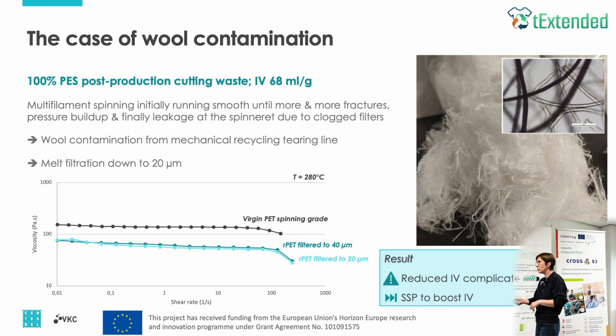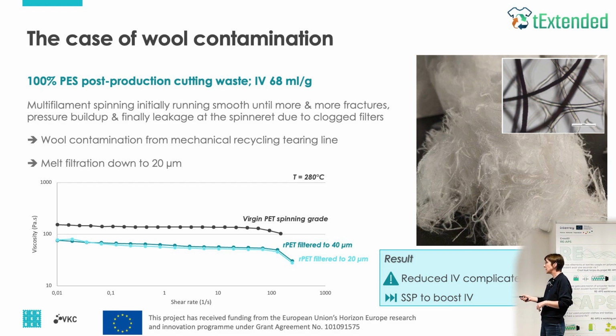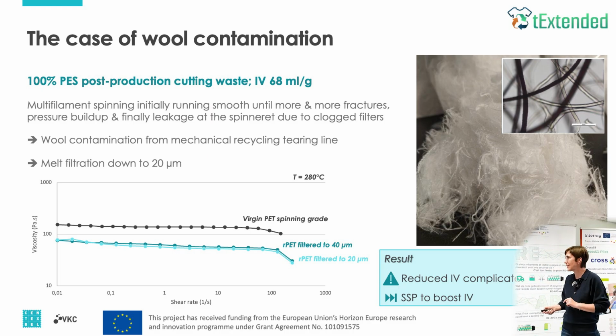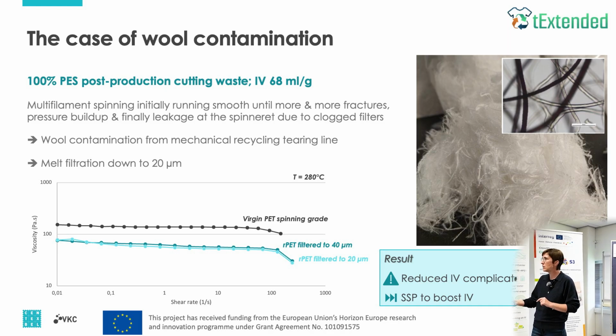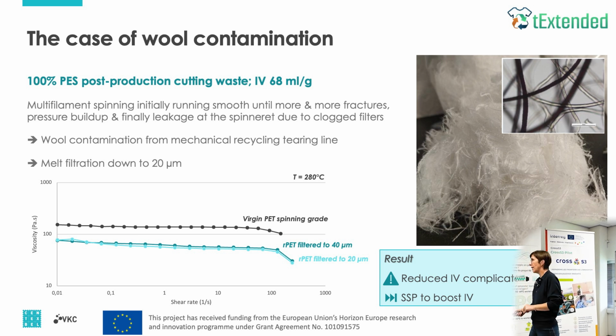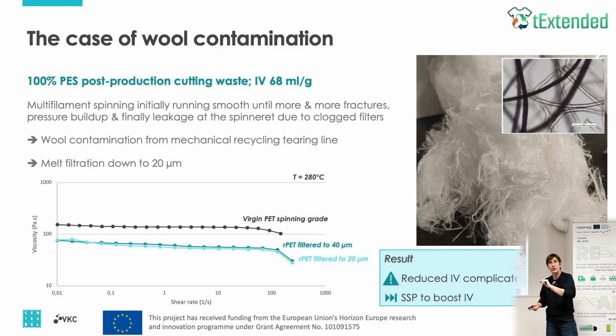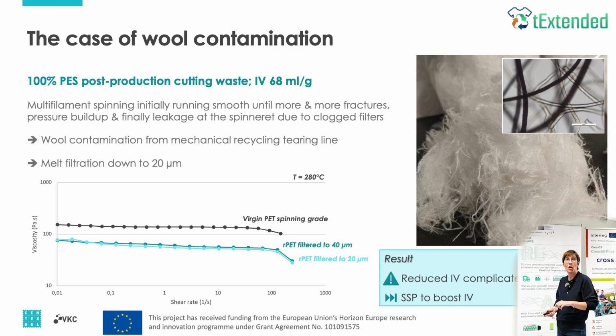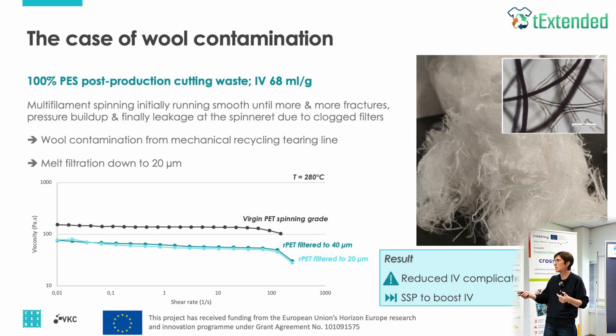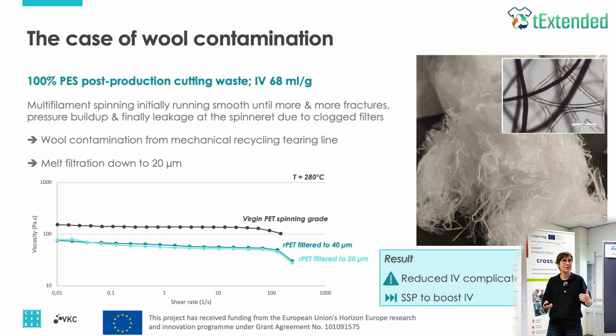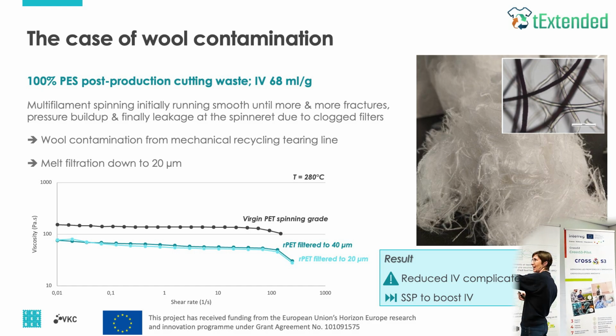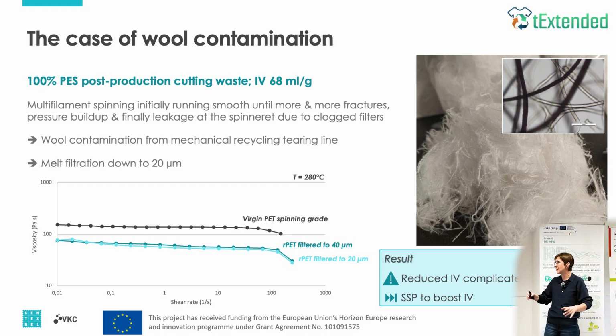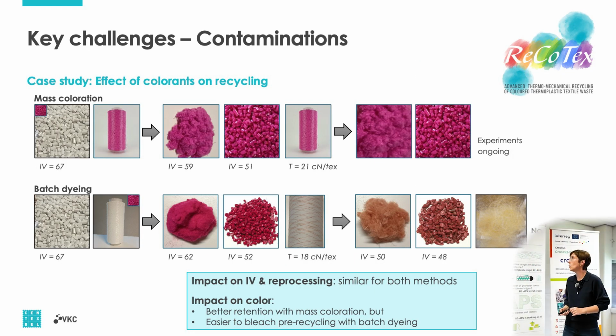Then okay, you can say we can try to filter it out, so we try to filter with a 20 micrometer and 40 micrometer filter, but take into account what you're filtering out. This is the rheology of a virgin polyester. These are the rheology curves of the same polyester, recycled polyester with some filtration. So you see a drop here in your viscosity. This is coming back to the other challenge, viscosity. So we are filtering something out to reduce contamination, but we are having an impact on our viscosity for polyester due to shear effects. So then you need to restore this back. You need to boost again the viscosity of your polyester to make sure you go back to a virgin material. So all those different actions you're taking go hand in hand, because one action you take to filter something out is affecting some properties of polyester, and you need to work on restoring your polyester chains to avoid this contamination.